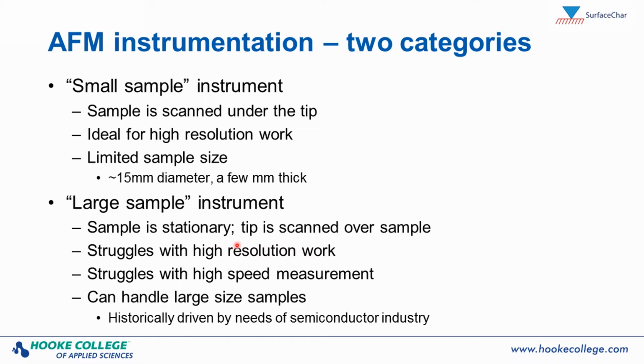So every design has its pros and cons. The con of a large sample instrument is that typically it will struggle with higher resolution work, because the motion and detection are both done by the tip. Whereas in a small sample instrument the motion is done by the sample and the detection by the tip, which enables better signal to noise ratios. Here the tip is doing all the work, so it can compromise high resolution measurements. It can also struggle with high-speed measurements because the samples can be very big.